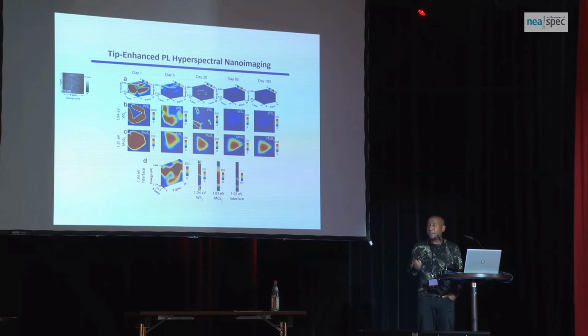Now I'm going to tell you a story that explains this data, and this is the best story we came up with. It's known that these 2D materials are sulfur vacancy rich on the outer layers, particularly those made with CVD. Those of you who work with CVD samples know this. The sulfur vacancies are rich on the outer layer, and they are a thermodynamically stable region for oxygen substitution. So oxygen finds it energetically easy to substitute at those vacancy regions, and it works itself inwards, oxidizing the material. That's why it starts from the outer edge of this material and starts to degrade.